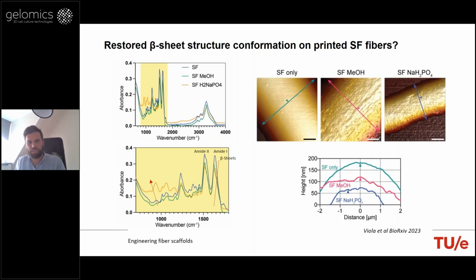And we also went further on trying to understand if from the molecular organization there was any evidence that by shearing the material out of a small nozzle, we are basically achieving the organization of the crystallites and the beta sheet structures inside of each printed polymer filament. We look at AFM, so atomic force microscopy, and we observed that there was kind of a shrinking and more striations on the sodium phosphate treated printed filaments that led to a smaller diameter and more confined filaments, and that we attributed to a more aligned construct compared with the silk-only fibers not treated either with methanol or the sodium phosphate.